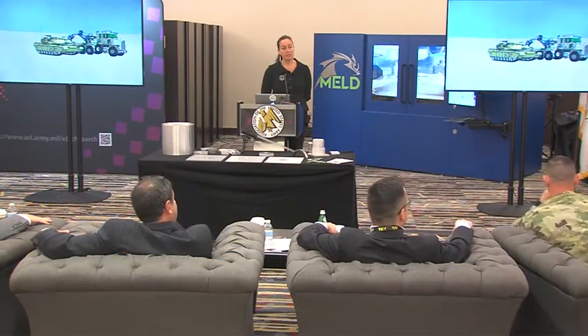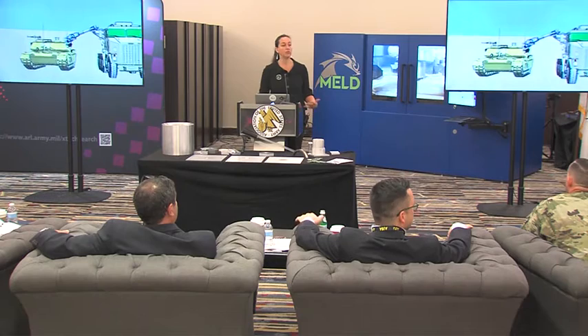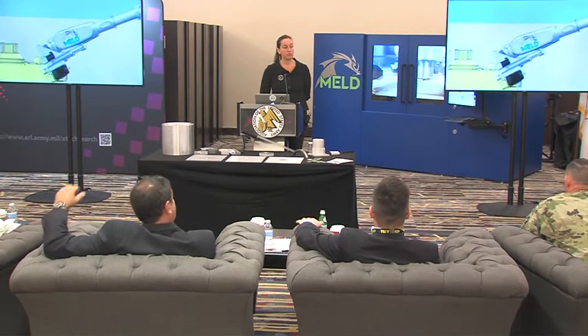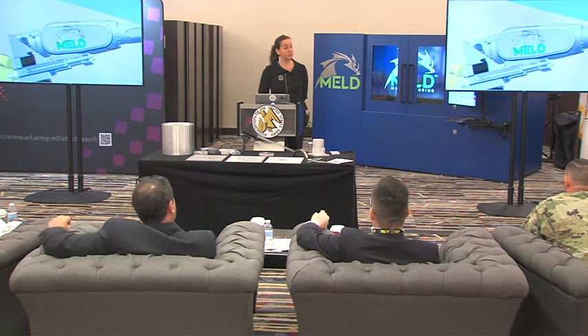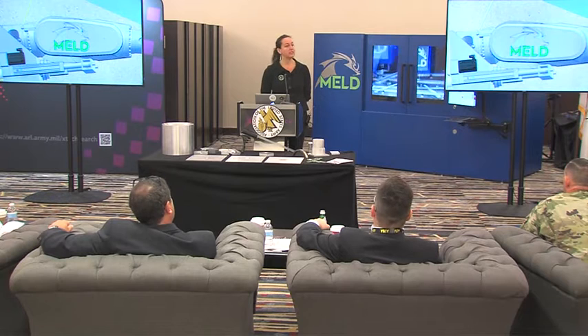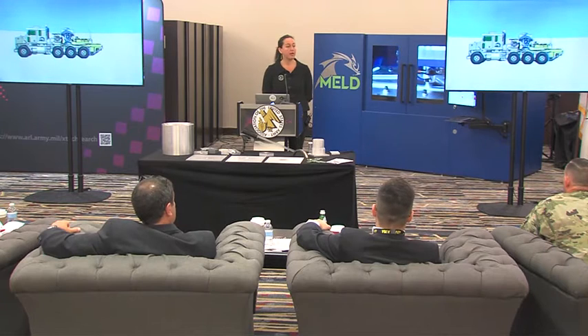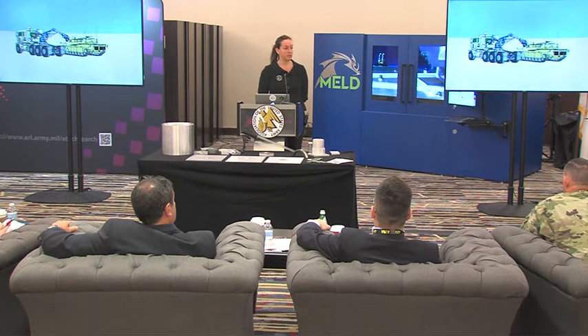I was wondering about the surface temperature when you're doing the application of magnesium. When you were building the magnesium part, did you measure the temperature of the material? In all cases, the temperature of the deposited material is going to range between 60 and 80% of the melt temperature. That's a good rule of thumb. There are opportunities to control temperature if there's some desire to do that. And we do have the ability to control ductility over strength, for example, in that way, if needed. But in all cases, you're going to see about wrought properties from the MELD material.